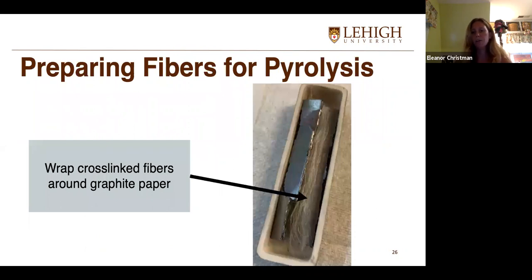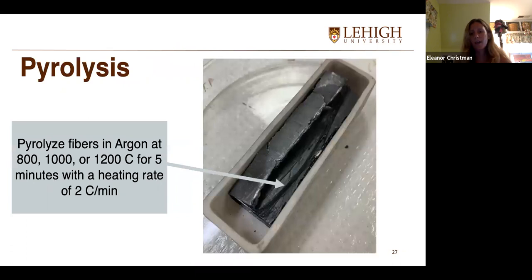I first prepare these fibers for pyrolysis by wrapping them around graphite paper. This allows there to be tension in the fibers so that they don't shrink as much. And we use graphite paper because it's just made of carbon, so it's not contaminating our sample at all. After preparing them for pyrolysis, I put them in the tube furnace for pyrolysis in argon at 800, 1000, or 1200 degrees Celsius for 5 minutes, with the same heating rate as before, 2 degrees Celsius per minute.